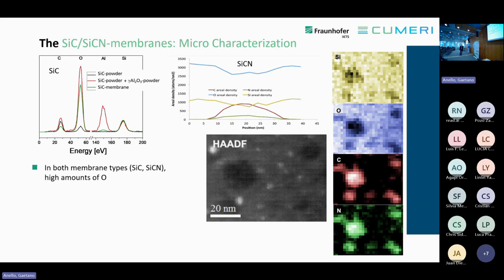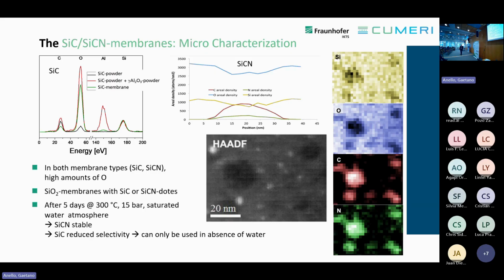However, we made stability tests with these membranes under harsh conditions. We treated them over 5 days at 300 degrees C and 15 bar in a saturated water atmosphere. And surprisingly, the silicon carbon nitride was stable. We measured the same permeances as before. So in principle, we can use this membrane. It seems that the dots are stabilizing the silica. For silicon carbide, unfortunately, we got a reduced selectivity. So principally, we can use it only in the absence of water. There's not enough hydrothermal stability.